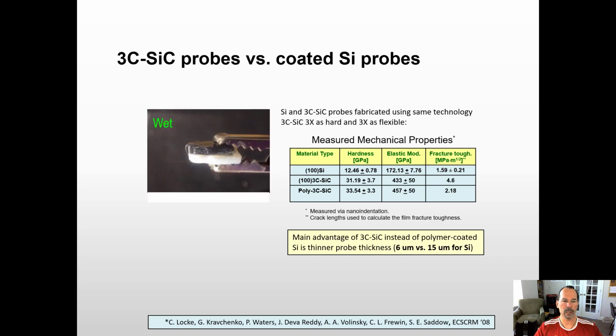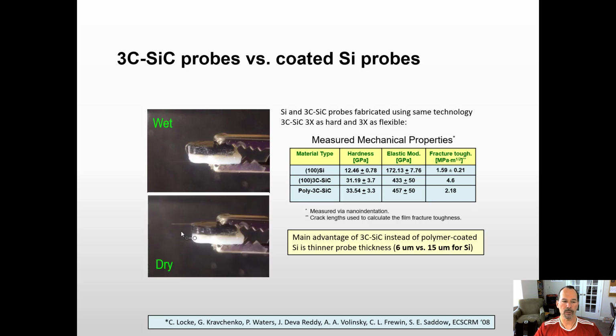So one bit of data I want to show you is shown here. Here we see a silicon probe glued to a header, a surgical header, with the silicon carbide probe glued here, cubic silicon carbide, both the same length, same form factor. After dipping in PBS, due to water tension, this probe literally bent more than 90 degrees to touch the plastic, and after drying, it released.